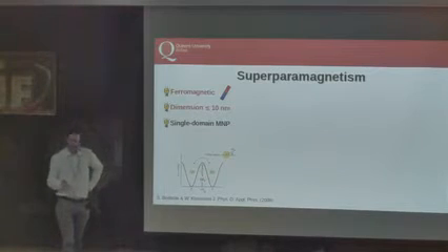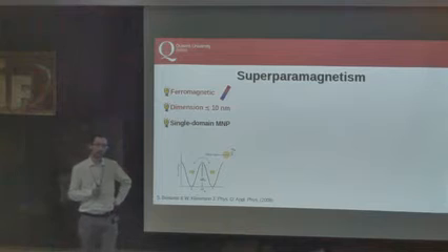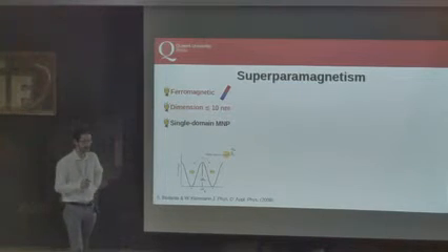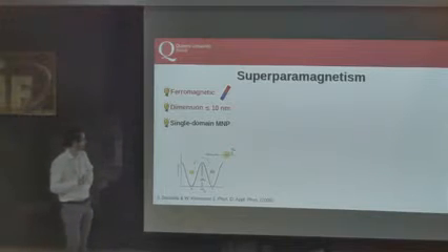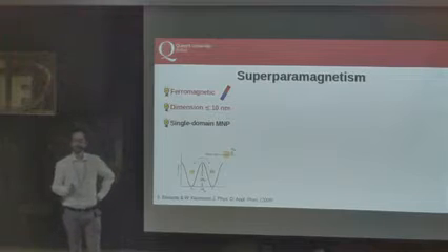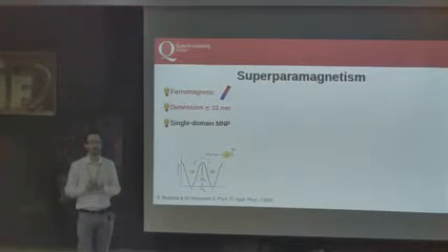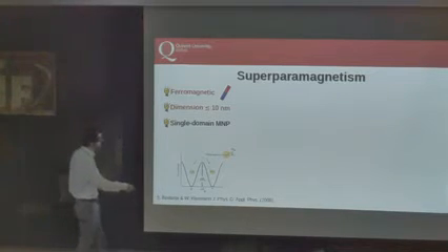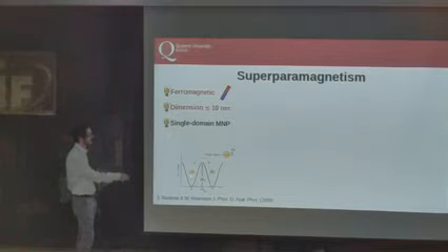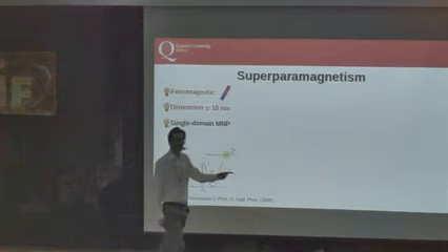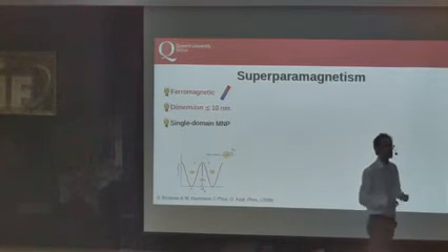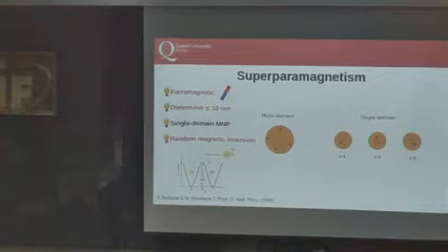Now, the height of this barrier depends mostly on two parameters. One is the magnetic anisotropy, which I think for this particle is 10^4 ergs per cubic centimeter, if I'm not wrong. And the other is the volume of a nanoparticle. So the larger the nanoparticle, the larger is this barrier. So what does it mean? It means that if I have a large nanoparticle, there will be no thermally activated spontaneous jumps from one valley, from one orientation to the other. However, if our nanoparticle is very small, as an effect of the thermal agitation, the internal magnetization density can invert randomly. And this random magnetic inversion at high enough temperature is called superparamagnetism.